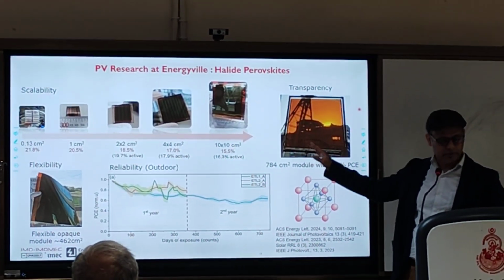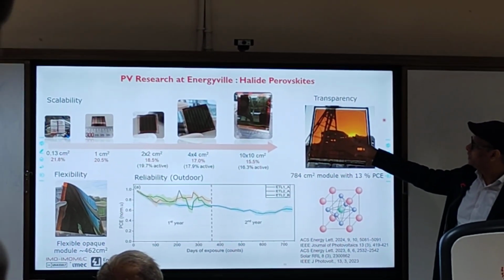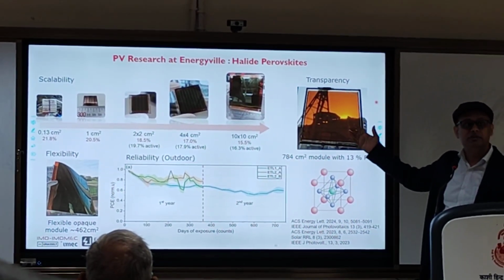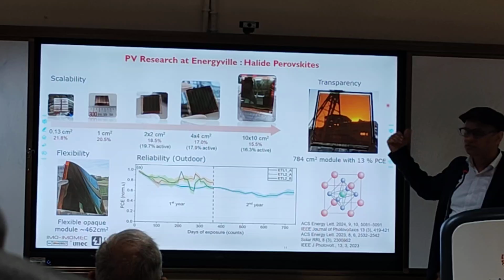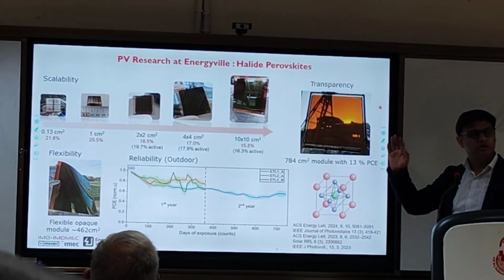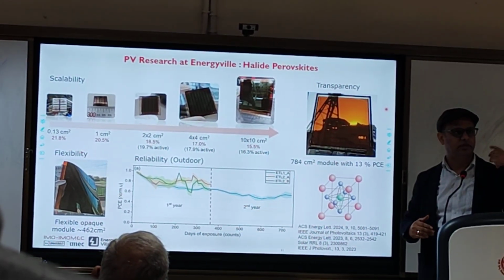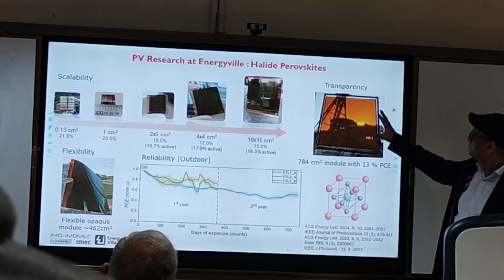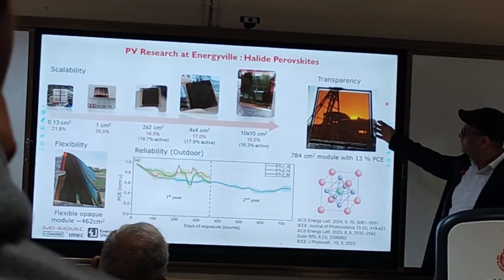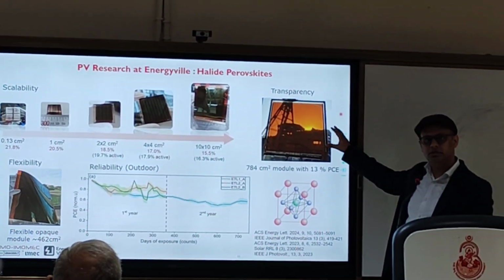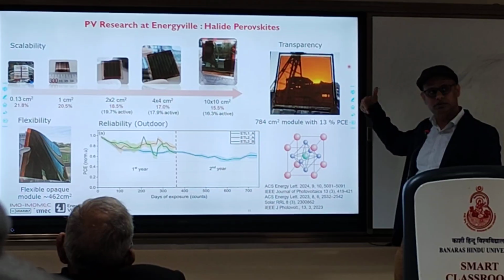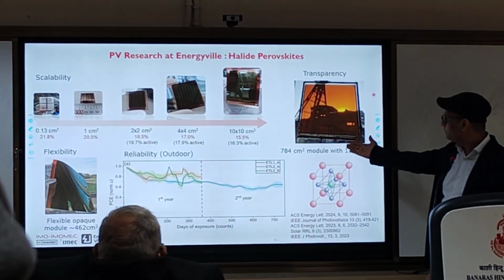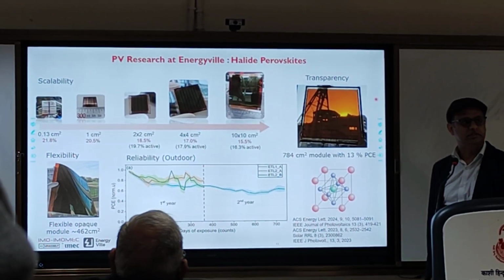That's quite nice. But as you can see, these films look okay, but they don't have functionality, as in they are not transparent. The goal is to put them on windows where you can see through a little bit. So we started working on transparency. Here you replace the top electrode, which is typically copper or something, with ITO, which is transparent. You also have a very large device with decent efficiency, 13%.